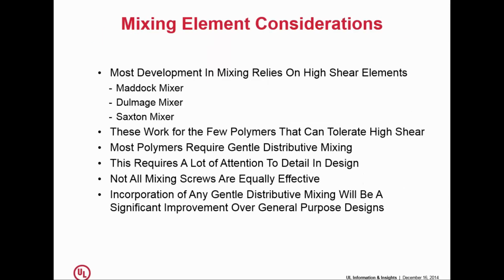Now, when you get into mixing devices, be a little bit careful, because most of the mixing devices that have been developed, especially in the early years, to improve homogeneity in materials are very high intensity, high shear devices. Things like Maddock mixers and Dulmage mixers and Saxton mixers. You look at the design of these things and you see, well, we're really beating the heck out of the material. If the material is very shear tolerant, a material like polyethylene, for example, you can get away with this.